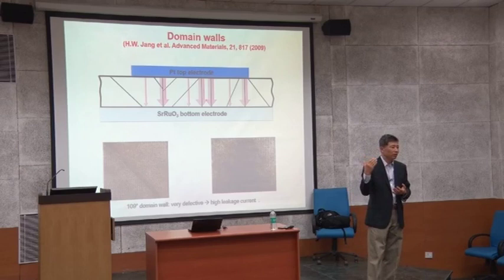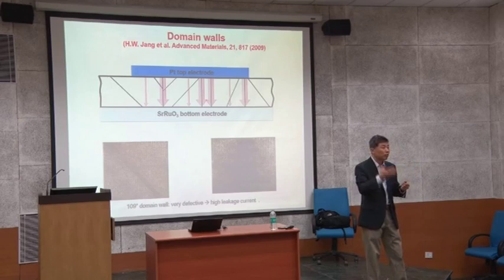This bismuth ferrite itself, its band gap is relatively low, like 2 point something eV. And creating a lot of charge carriers inside here comes from many different reasons. But the domain wall region has a lot of broken bonds and a lot of defects, and the chemistry is not very good. For example, you have some bismuth deficiency at the domain walls. Usually you freeze all the carriers when you go to low temperature, and that's why you can measure at low temperature. When you go to high temperature, more carriers come because the gap is low, especially near the domain wall region, where the gap is even lower. That's why it is created.